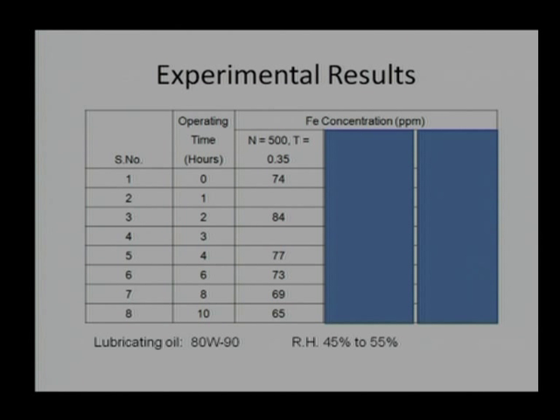We say that we bought a new gearbox, and we know whenever the gearbox is new, it should not be loaded completely. So, what we selected was almost zero load and 500 rpm speed. N is given in RPM, that is 500. We will not use a unit symbol here because RPM is a common unit, and torque as 0.35 Newton meter. We did not apply any torque from the dynamometer, but we know that during assembly there will always be some sort of misalignment. There will be some resistance from the assembly, and that is given as 0.35 Newton meter torque.